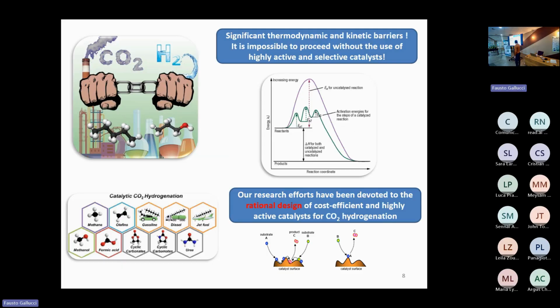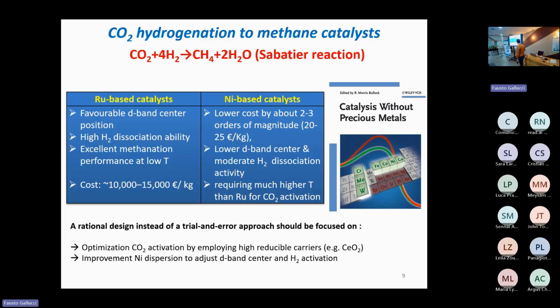Thus, in our efforts we have focused on the rational design, instead of following a trial and error approach, to synthesize cost-efficient and highly active catalytic materials. Let's at first exemplify this rational approach on the basis of the CO2 hydrogenation to methane through the Sabatier reaction. For this particular reaction, the most active catalysts are noble metals, like ruthenium, which exhibits a favorable d-band center position in conjunction with high hydrogen dissociation ability, thus offering excellent methanation performance at very low temperatures, but with a cost of about 10 to 15,000 euros per kilo.